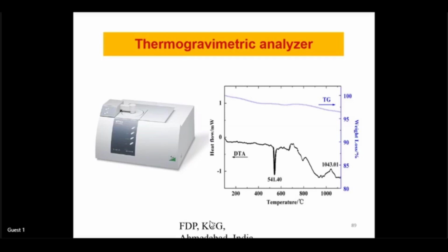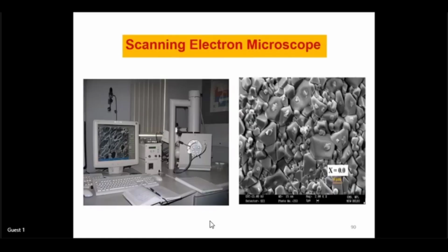So if you design any device, but after heating, if the device shrunk, then the material is not very stable. So for temperature stability is very important, and we have to check using the TG and DTA curve. Fine. And I mentioned to check the surface morphology, whether the formed particles are uniform, agglomerated, or not showing proper shapes, and how much void is there, that can be tested using the scanning electron microscope.